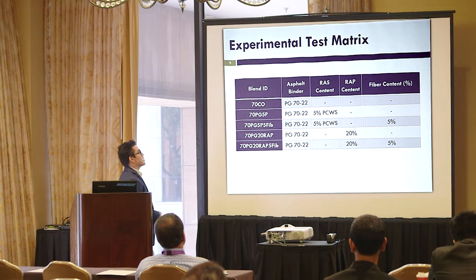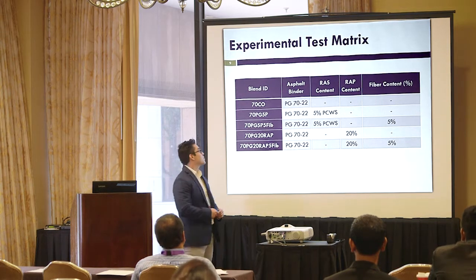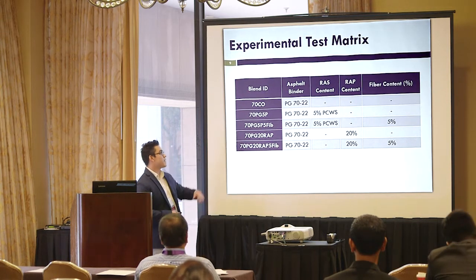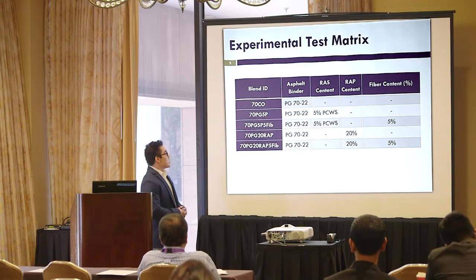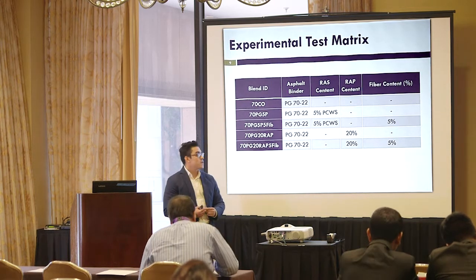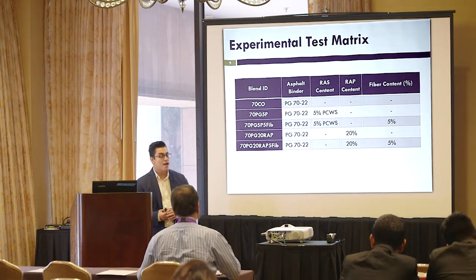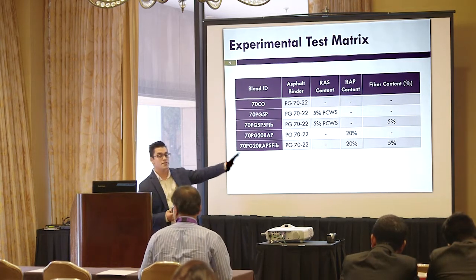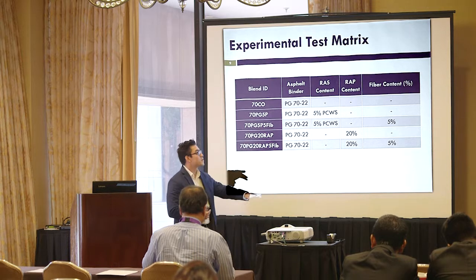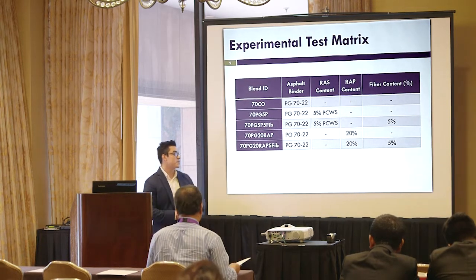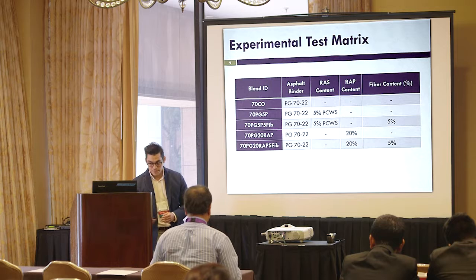This table shows the experimental test matrix that I used for this project. We have 5 different mixtures or blends. We use a PG 70-22. We incorporate 5% RAS, 5% RAS plus 5% fibers. We also use 20% RAP and 20% RAP plus 5% fibers.